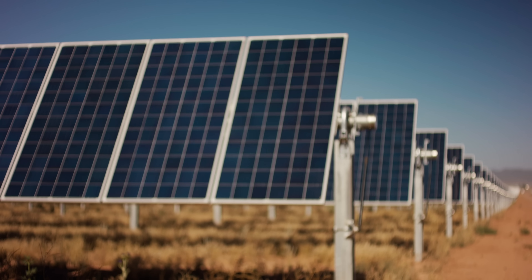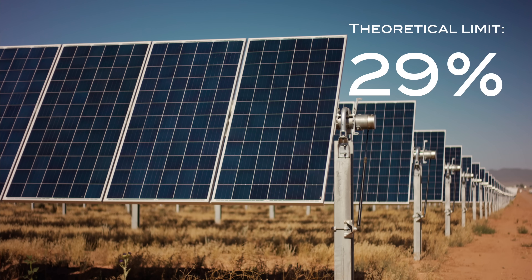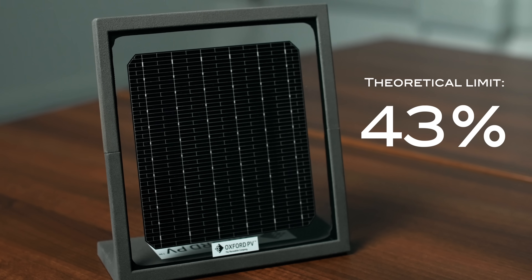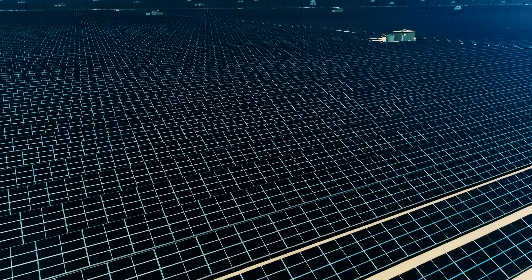So we decide to combine a perovskite solar cell with a silicon solar cell together in a concept called a multi-junction solar cell. The perovskite is designed to absorb in that blue part of the spectrum where there's actually more energy, and the energy it can't use it passes through to the silicon, which converts the rest of the photons — effectively raising the theoretical efficiency potential of that device. Silicon is limited at the theoretical maximum to 29%, and the closest anyone has gotten is just under 27%, with manufacturing at 25%. If you combine these two solar cells together, that 29% number changes to 43%. That's not an incremental improvement — that's a step change that can be transformative for deploying PV at a much larger scale.